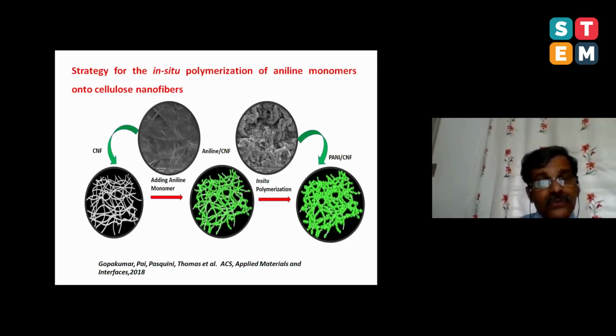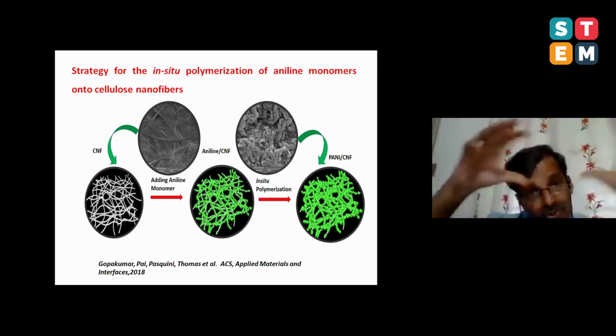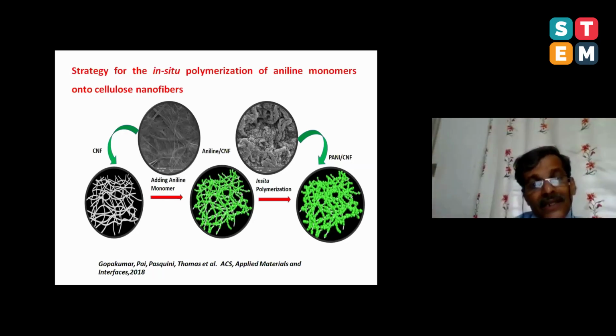My research group, my PhD student Dibu, has done some exciting work. He extracted nanocellulose from waste. Then he did an in situ polymerization of the structure with aniline. We made nanocellulose, we put in aniline, and we did in situ polymerization. And eventually what we got was a beautiful nanocellulose paper. This is a nanocellulose paper manufactured by Dibu and my research group in cooperation with Brazil.